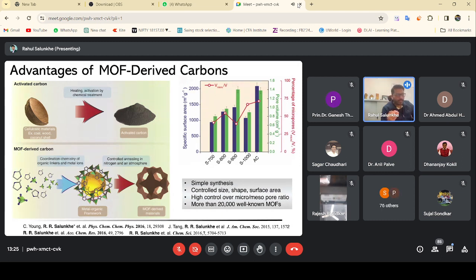Now, after controlled annealing in a nitrogen environment or an air atmosphere, we can convert this kind of metal organic framework into either a porous carbon or a metal oxide. Because of that, they have a very simple synthesis, as I have illustrated here. They have a controllable size.